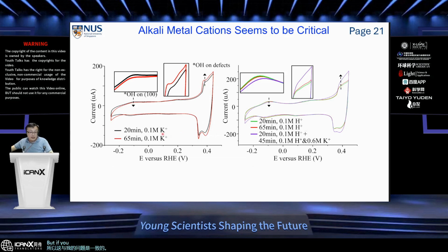But if you remove the alkali cation, if you remove the potassium cation and replace it with protons, and then repeat the experiment with 20 minutes and 65 minutes, as shown in the green and the red curve here, they are much less different. They are kind of similar, a slight difference, but nothing like if you just put the potassium cation back, you will see a huge change again. So this tells us that the HER, the hydrogen evolution reaction, which is certainly happening where you have a lot of protons in the electrolyte, cannot be solely responsible. It seems like the alkali cations play a role.